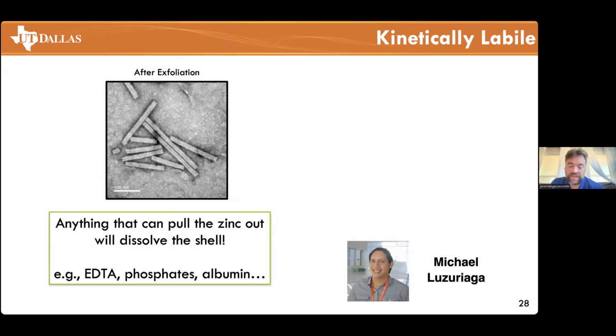Now, I had mentioned the kinetic lability before, and I'm re-emphasizing this with the tobacco mosaic virus. You can see here, these were actually removed from a ZIF. You can see they're structurally pristine, completely unharmed. What we also found is that in addition to chelators like EDTA, phosphates and albumin and protein are very good at removing the zinc. And they will completely strip the ZIF away, but much more slowly than EDTA. And so essentially what you have is biological anions or macromolecules coming and disassembling your external polymer.